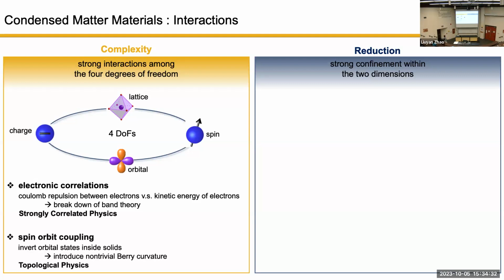Another example of interaction we can take a look at is the so-called spin-orbit coupling. That's a relativistic effect at the atomic scale. That is to say that when your electron orbits around your core, this orbiting behavior of charge is going to create a pseudo-magnetic field. And the pseudo-magnetic field is going to act on your spin degree of freedom. So the field acts on spin, and then it will give you an energy scale. If that energy scale is big enough, you can actually flip the orbital orders inside the material. This kind of flipping of orbital orders has the terminology of a band inversion in material science. Then that will give us some topological aspect about the electronic wave functions in the material.